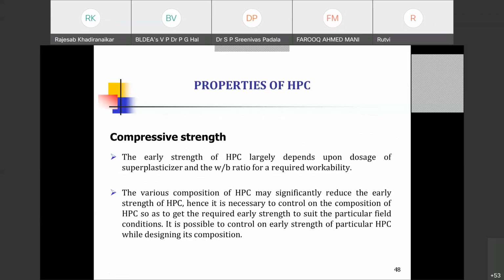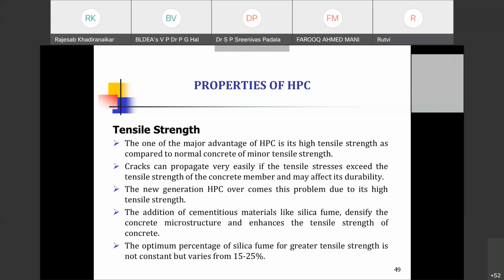The early strength largely depends on the dosage of superplasticizer and the water-binder ratio. The various compositions of HPC may significantly affect the early strength of HPC, and it is necessary to control the composition of HPC so as to get the required early strength to suit the particular field conditions and control the early strength of your HPC. And another important property is the tensile strength.